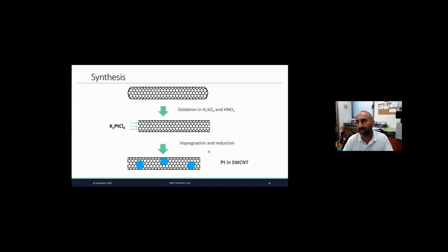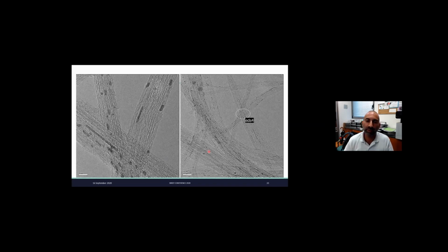So we do that by this method. That is simply impregnation of the platinum salt inside the nanotubes. And what we get is the platinum that is inside the carbon nanotubes. And you can see here, it's really following the carbon nanotubes all the way. This is a very low mag image. So we see the nanotubes all over the place, inside the nanotubes and not outside.